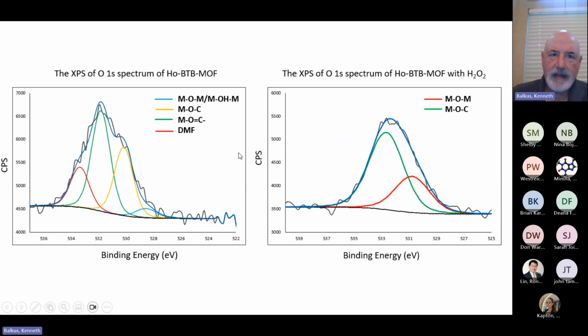Also interesting with this particular one is that if you look at the XPS, this is the oxygen XPS, you'll actually see this tiny peak here of some oxo bridged. And so this was the first time we said, okay, you can actually get a little bit of oxo or hydroxo bridged clusters in there. It's mostly fluoro bridged, but you can get a little bit of oxygen bridged. And if you add peroxide to the synthesis, you can drive it to mostly the oxo bridged. Since we first reported some of this chemistry 2 years ago, now people have reported a number of structures where they see a mixture of fluorine and oxygen.